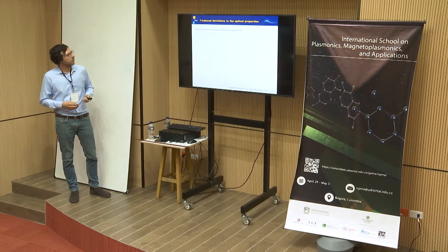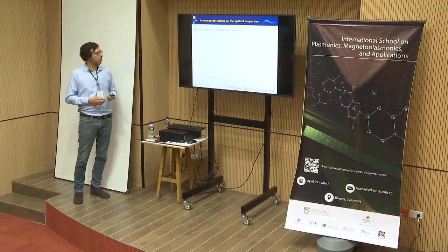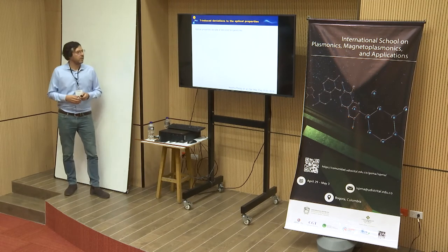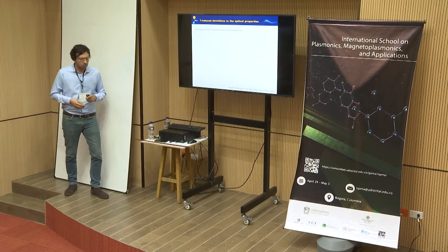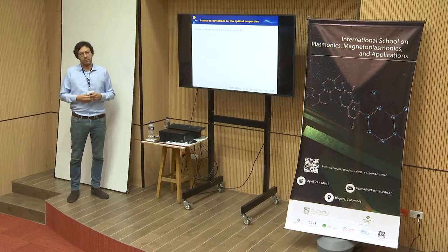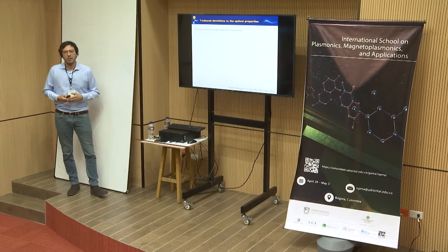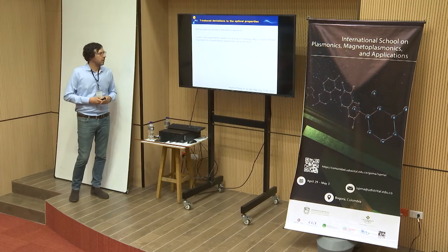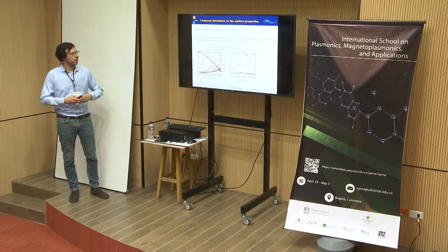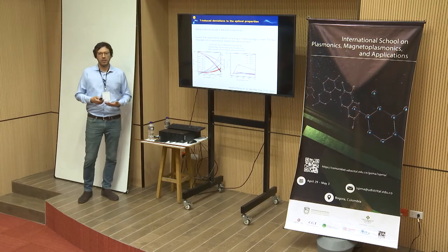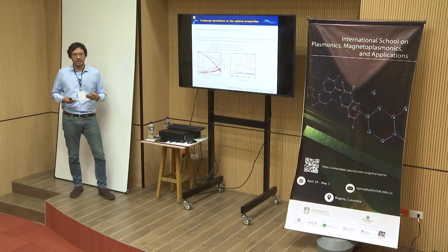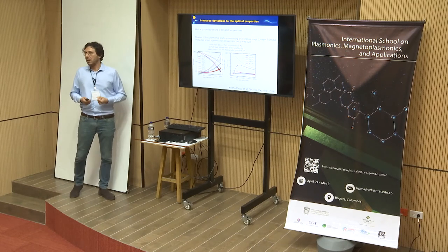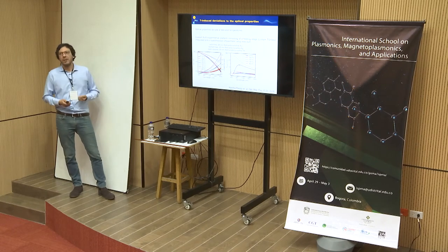So now, after this overview of solar evaporation, I want to switch to the high temperature regime. And it is important to say that the optical properties of materials usually change at high temperature. So the materials that, for example, show a specific epsilon prime, so the real part of the permittivity, if you start heating up, they will lose this metallicity, so they will become less plasmonic, which means they will generate much less intense electric fields on your nanostructure.